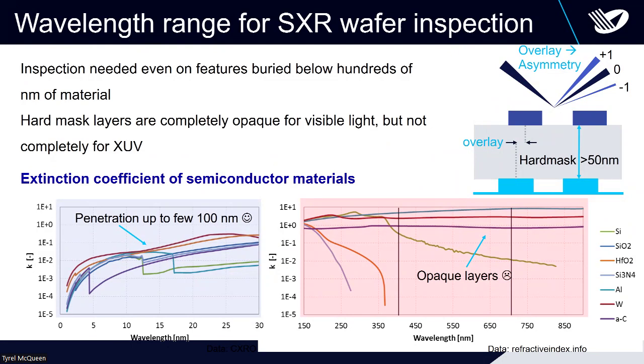The other part about soft X-ray that is pretty nice is that it can measure through a lot of buried layers. So that comes to one question that was there earlier. Particularly these hard masks, these special etch materials are often completely opaque for visible light. And that's a bit better in the soft X-ray range. So showing here the absorption coefficient of a lot of different materials that are shown there on the left in the soft X-ray range, and in the visible wavelengths range, it's the same Y scale.